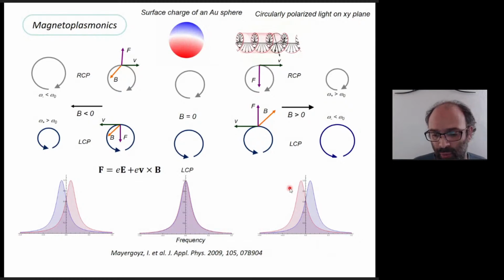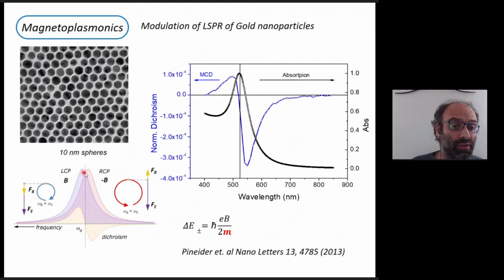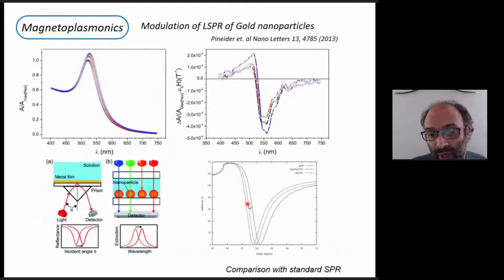So if you take an experiment in which you change the magnetic field from positive to negative, then you can move back and forth your plasmon resonance, okay? If you measure the difference between these two split peaks, you will get this kind of signal, okay? It's kind of a derivative of the optical peak. Now look at this. You remember we talked about SPR, okay? So this is the reflectogram, so how light is reflected off a plasmonic surface. And look at here at the shape of the magneto-optical response of plasmon resonances in a magnetic field. Okay, so you switch from a plasmon resonance, which is a peak, to a derivative.